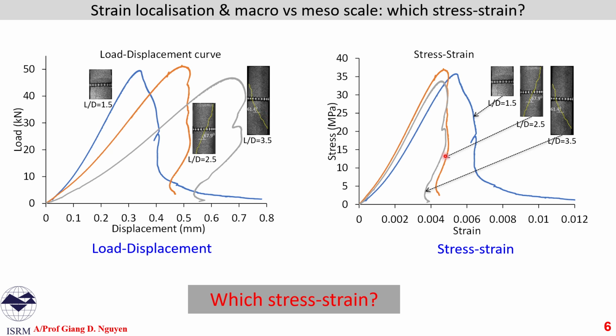But if we normalize everything as we usually do to get stress and strain behavior, we can see that the elastic stiffness is almost similar. Some small variation here is mainly due to the inhomogeneities of the material across the three different specimens. The post peaks are very different, so there is stronger softening or snapback for the longer specimens, say length to diameter of 2.5 and 3.5.